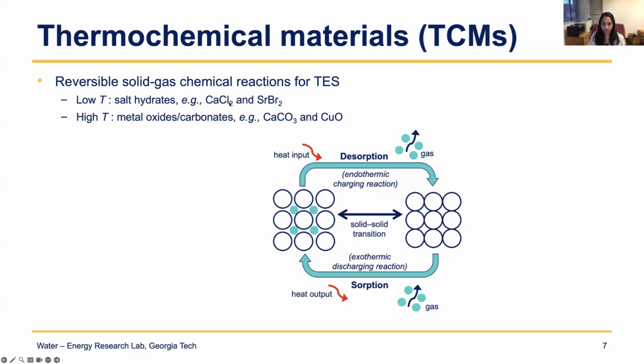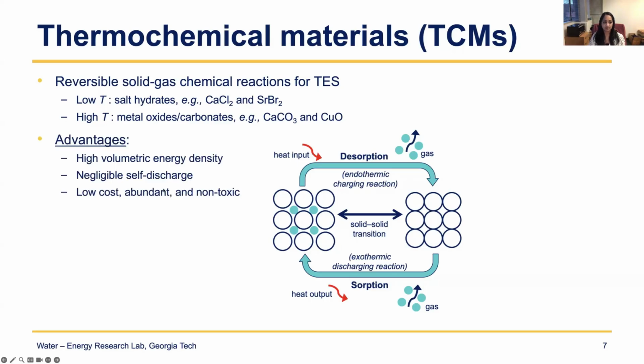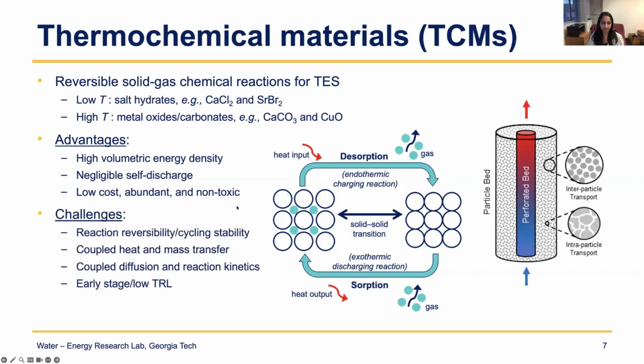Instead of a salt with water vapor, we can also have something like calcium carbonate, which will desorb CO2, carbon dioxide, and become calcium oxide, and then reintroduce the carbon dioxide to form calcium carbonate, or limestone. That is a very high temperature reaction, around 800 degrees Celsius. So we study that for industrial process heat. Again, the main benefit of these materials is very high volumetric energy density. Also the storage is lossless because it's a chemical reaction and all the energy is stored in the chemical bond, so there's no self-discharge over long durations of storage. And we work with materials at a very low cost, like I said, limestone and salts. These are very abundant and non-toxic as well.